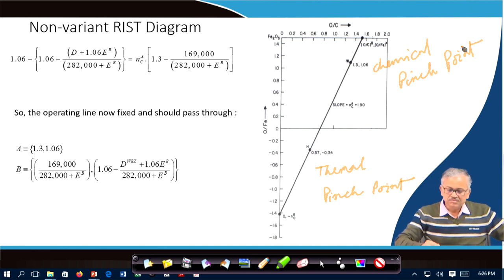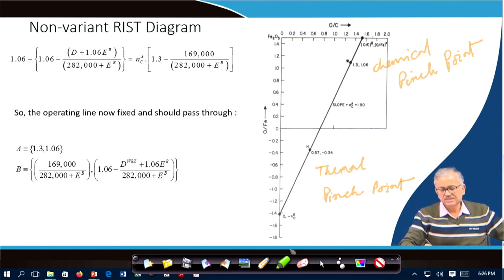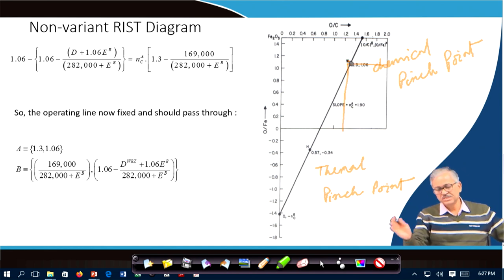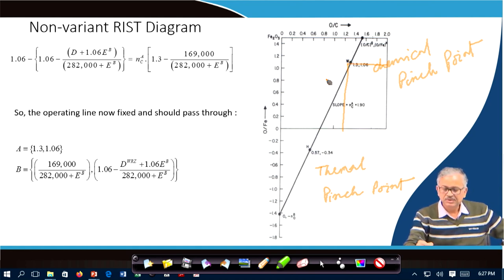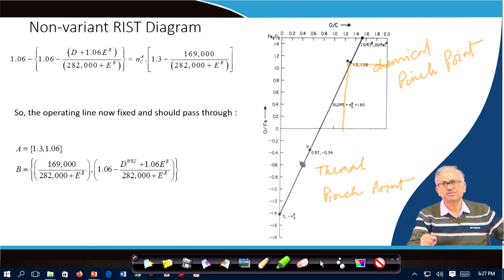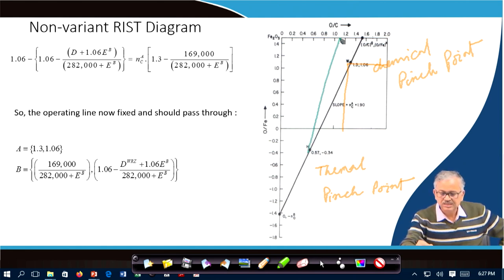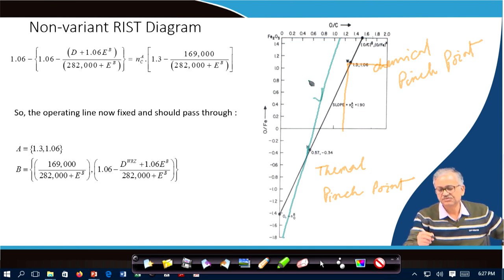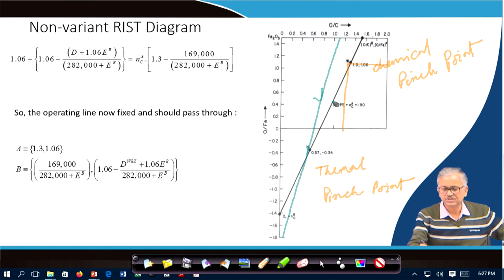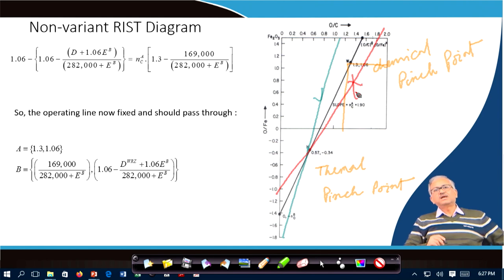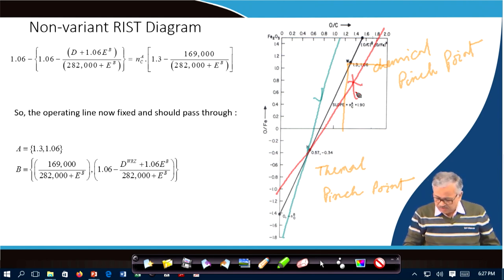To summarize: no operating line can go beyond the chemical pinch point W in that direction, as it would violate the FeO–Fe equilibrium. Lines on the other side (left of W) through H are feasible but less efficient. The line through both H and W is the most efficient — the optimum operating line with minimum coke rate.